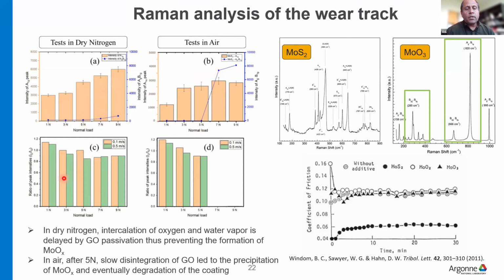Simultaneously, if you look at the GO peaks, this is the intensity ratio of IG by ID, where we can see in dry nitrogen, it's working fine, but in the ambient air after 5 Newton, exactly where we saw the formation of MoO3, the GO peak is disappearing. As per the previous literature, MoS2, this is for thin film MoS2, has a lower friction, but moly trioxide has a higher friction. What we believe is happening is that at a higher contact pressure, there is a slow disintegration of the graphene oxide that leads to the precipitation of this MoO3 and then eventually degradation of the coating.